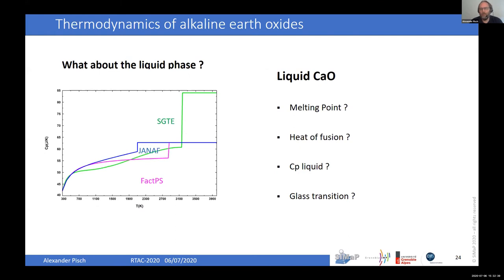But what about the liquid phase now? So we have a nice data set for the solid phase. And then when you look at the literature, you see it's a mess. So here I plotted just three versions of the liquid phase. You see Janaf, which was taken as a reference for the FACT pure substance database. They assumed a CP of 63 joules per mole and Kelvin, and a melting point, which is here, at 2,800 Kelvin. SGTE in their database assumed a much higher melting point, around 3,100 something, and also a much higher heat capacity in the liquid phase of 83 joules per mole per Kelvin.